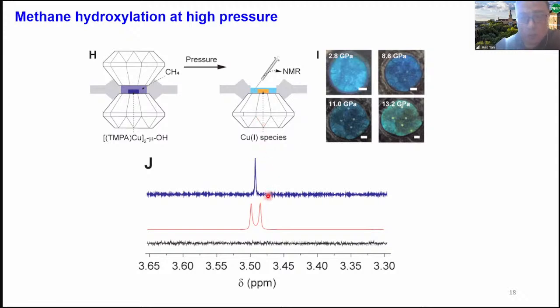So once we break the symmetry of this dicopper center, the bridging oxyl is such a strong oxidant that it can oxidize the CH bond in methane with a BDE of up to 105 kcal per mole. Are we saying every flaring oil field or gas field in Texas should have a high pressure device on top of it? Probably not, right?